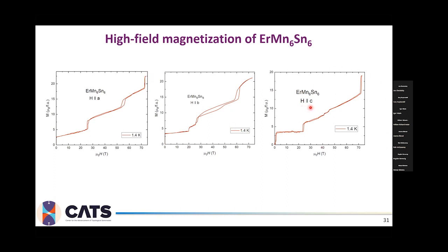Similarly, when the magnetic field is parallel along the C direction, we do see a very huge jump at 72 Tesla. It is followed by the saturation. When the magnetic field is applied along the B direction, we do see again one more transition at 62 Tesla. In that case, we do not see a clear saturation, but we definitely can say that the magnetization tends to saturate and probably will saturate shortly after our magnet limit.